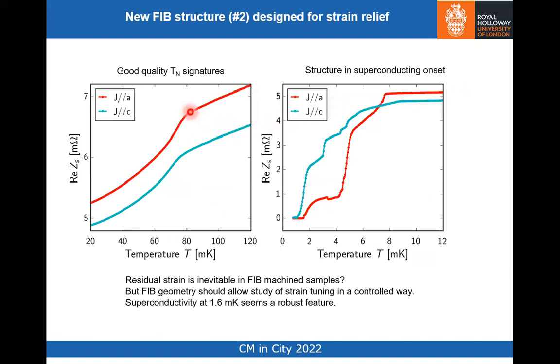And what you see then is that the Néel temperature is in more or less the same place for both field directions, but there are some shifts between the two current directions, for this is A axis and this is C axis. But then there's this rather ugly temperature dependence, which is indicative of residual strain that's probably inevitable in these FIB machined samples, because they're square cross section, they've got corners. It's probably very difficult to totally eliminate strain, but the message that comes out of that is that strain is important, and so we can turn that on its head and use the FIB geometry to apply strains that are larger than any residual strain in the sample, and use strain to tune the superconductivity in a controlled way.